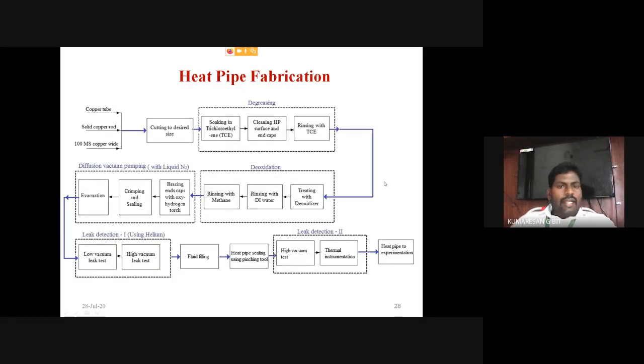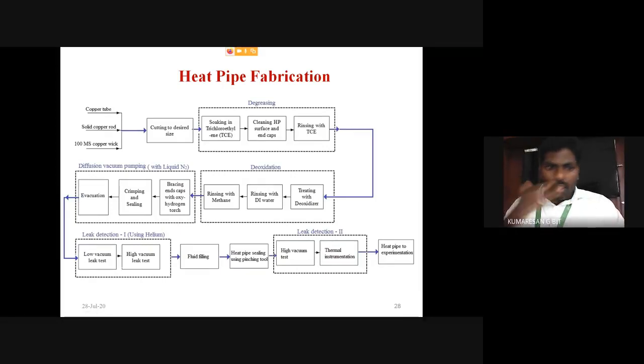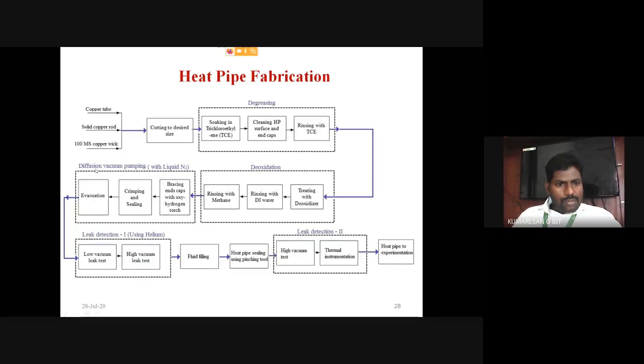The next, fabrication of the heat pipe. Here there are two major steps involved in the fabrication of the heat pipe. First one is the diffusion vacuum pumping process, then the leak detection process. These two processes are very important for the heat pipe fabrication. Then only does the fluid injection take place in the fluid injector. Before we take it for the diffusion vacuum pumping and the leak detection test, the copper tube, solid copper rod and the mesh wick structure are cut into the desired sizes.